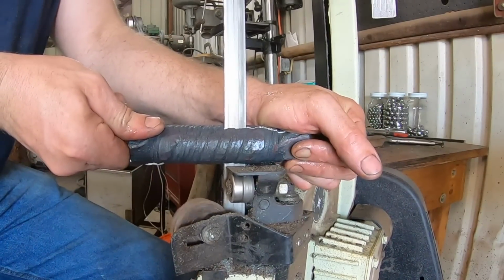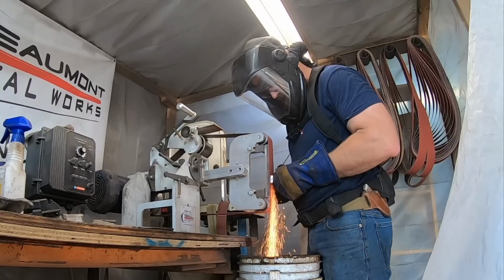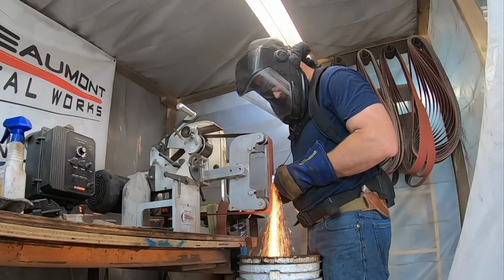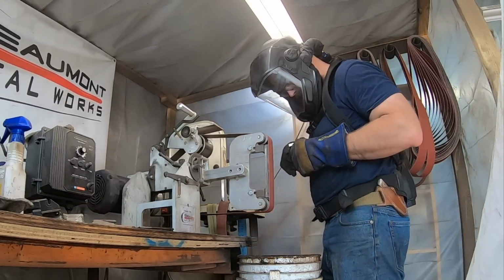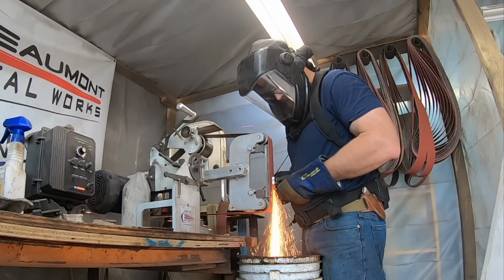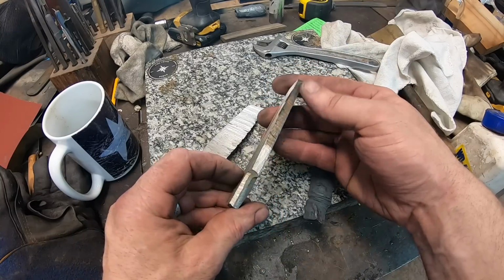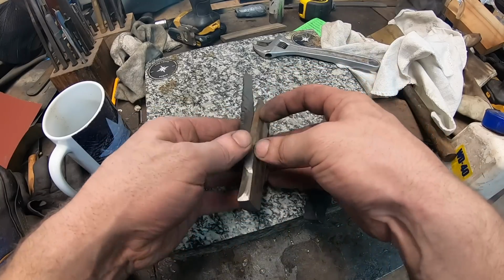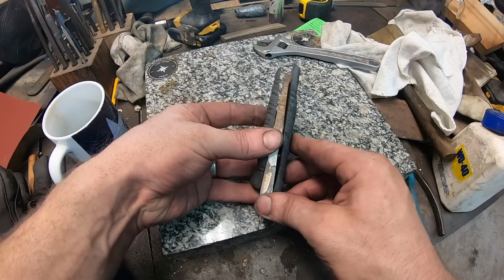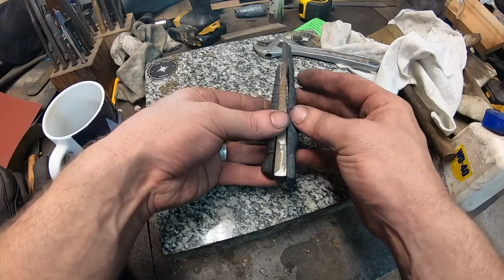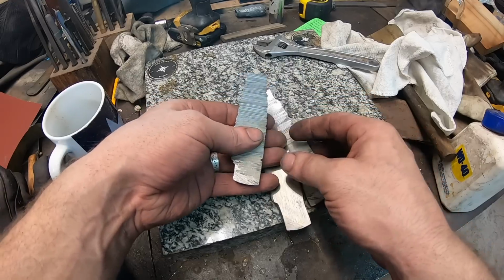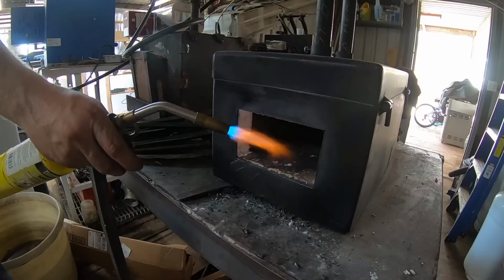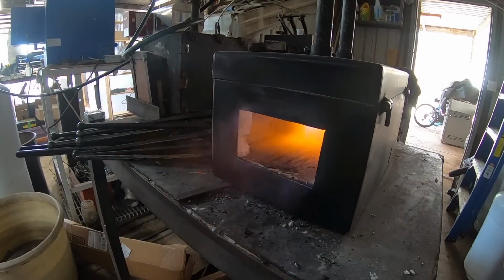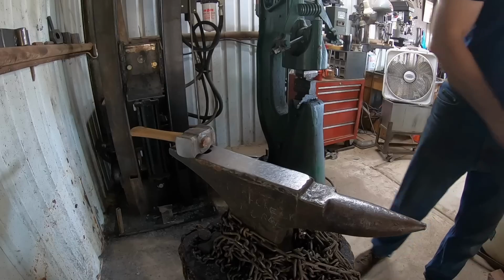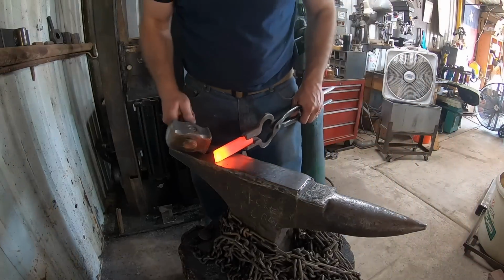The reason I'm doing this is because when you twist a billet, there is a range of patterns that present themselves throughout the thickness of the billet. And the pattern that I'm after is towards the center. So after cutting and grinding, you'll see what we have here, a slightly tapered billet with the end there that doesn't have the twist on it, and that's for the tang. So now we can go ahead and forge the blade profile.